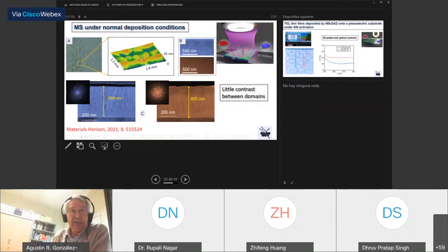We have crystallization. This is TiO2, and it is rather unusual to get a crystalline form of titanium dioxide by magnetron sputtering at room temperature. So we see some difference, but the differences are not dramatic. So we are indeed producing some densification in these areas and less densification in this area. But of course, magnetron sputtering in a normal configuration is a typical technique to produce compact thin films. So we cannot expect too many changes.